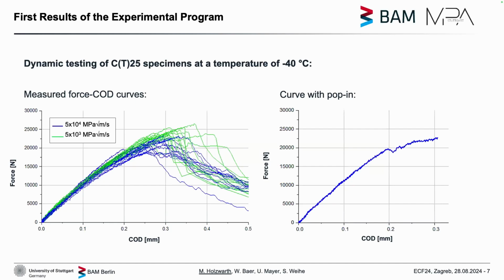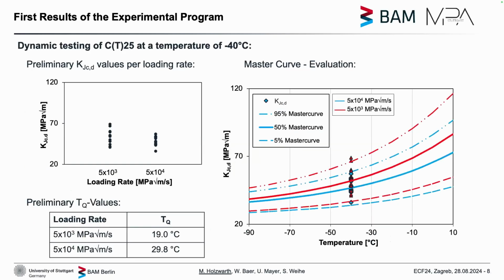And after we have done our tests, we got these force COD curves here, and a lot of them showed pop-ins. And according to the standard, we have now to evaluate these pop-ins if they are significant or not. In this case, this one would be deemed significant, which means we have to evaluate the test at the point where the pop-in happened. Then we have done this evaluation for all of the curves. We performed the evaluation according to the standard, and then we got our KJC dynamic values, which are shown here.